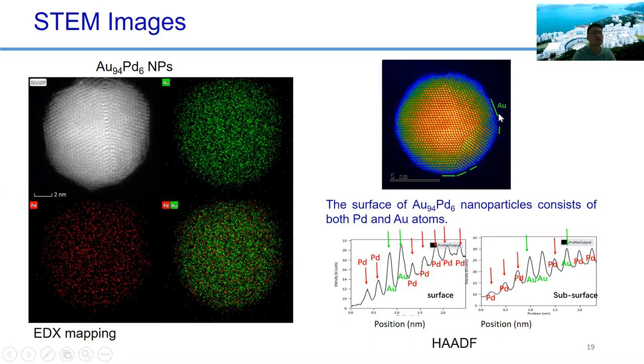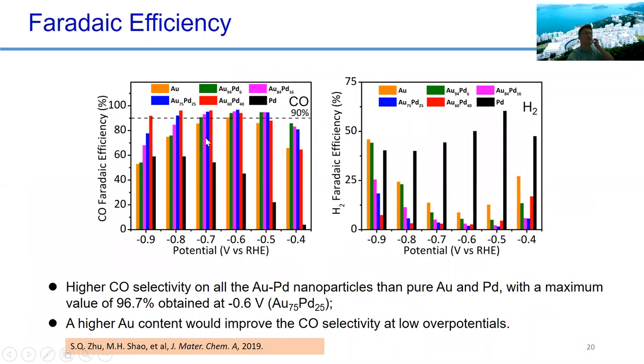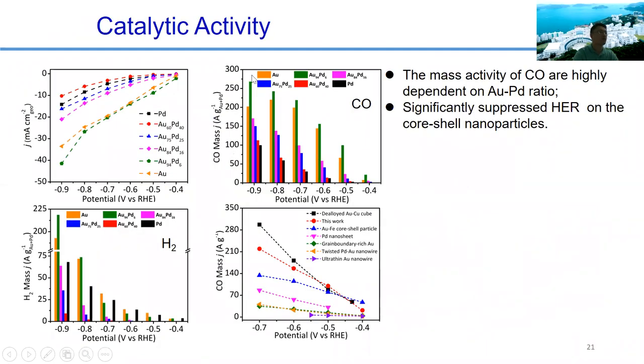You can see that the surface is still majority palladium and some positions have gold. And we can find that the nanoparticles also have very high CO selectivity, the majority of them higher than 90%. And we can also normalize it to the weight to generate the mass activity, right?